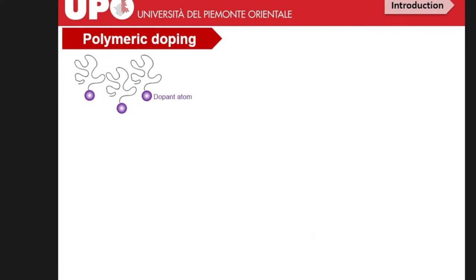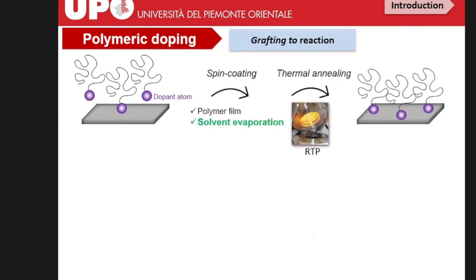So for making the doping process, we use a strategy called grafting to reaction. This strategy can be simply described in two steps. The first one is a spin coating, when we create a film of the polymer on the surface of the semiconductor. In this case, we eliminate the solvent. And then by rapid thermal processes, we promote the reaction of the polymer with the surface of the semiconductor.